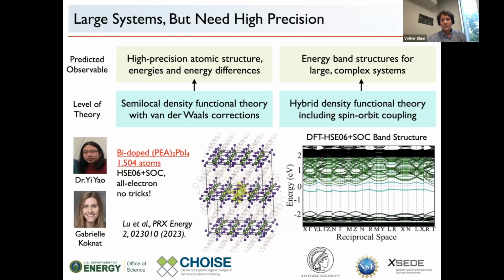This just worked, and you look at the orbital of where that individual extra electron on bismuth is. It's localized on the bismuth, which is the cyan atom here, and it's localized in the unit cell. And in the energy band structure, which we can also calculate, you see that this leads to a filled energy level in the zero temperature limit, which is actually pretty much flat. And this means that for purposes of defect calculations, the supercell is large enough to decouple the defects. The conduction bands of the material are the green bands here.